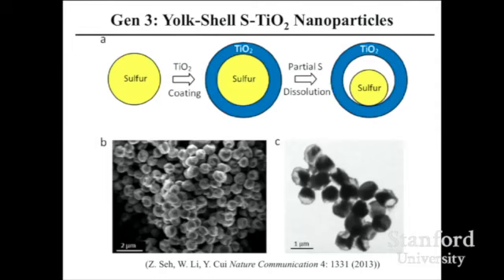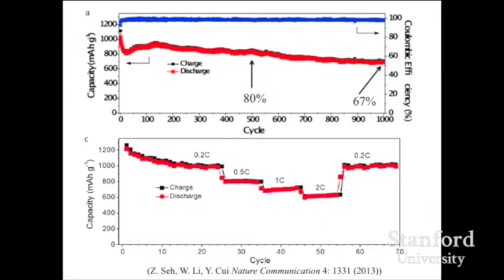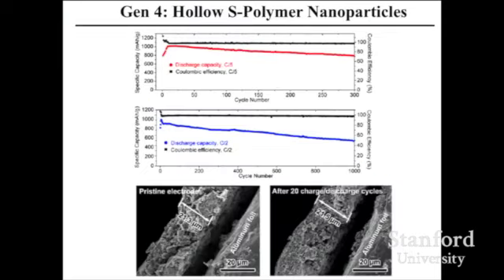Similar to silicon, pretty much we figured out silicon. We also want to use the same strategy for sulfur. If you can make this Yolk-Shell structure, using titanium oxide coating, polysulfide cannot leak out anymore. Volume can expand right here without cracking the coating. This is a beautiful sulfur, TiO2, Yolk-Shell structure. This runs even longer cycle, 1,000 cycles, with close to 70% capacity retention. So with this on and on, I'm going to skip this. Hollow particles also work well.